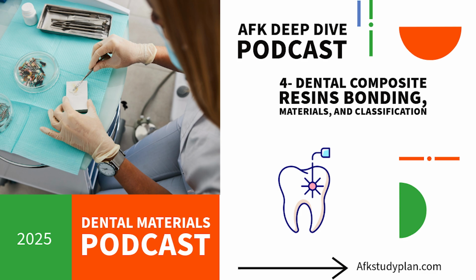Once that's gone, the acid creates these tiny, tiny pores on the enamel surface. Micro roughness. Exactly. The video described it as exposing enamel prisms, making it look like a honeycomb under a microscope. This massively increases the surface area and the surface energy. So much better for wetting and gripping. And usually they etch enamel and the layer underneath, the dentin, at the same time? Yes, simultaneous etching is common, and typically it's only for about 15 seconds. Usually. Though the PDF notes it might be a bit longer if the tooth has high fluoride content or for baby teeth, because their enamel's a bit different. And then rinsing is super important. Oh, absolutely critical. Rinse thoroughly with water, maybe 20 seconds or so, to get rid of all that acid.